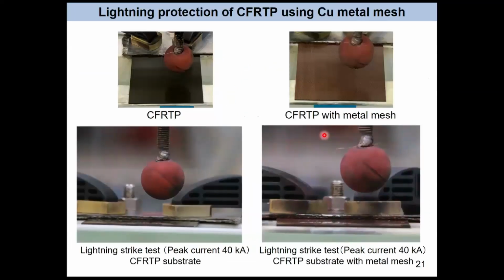Before we see the cold spray result, first I will show you the original CFRP sample result. This is the sample with no lightning protection. We can see severe damage of the CFRTP, carbon fiber fracture occurs, and we can also see fire on the CFRP. The next is CFRP with a conventional metal mesh, so with a lightning protection system.